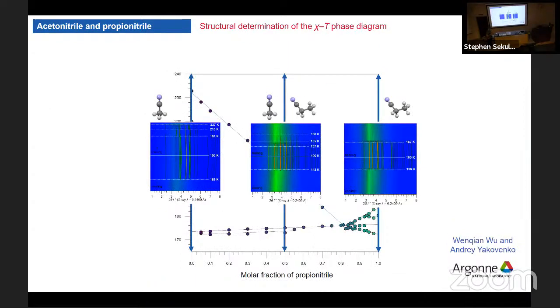As I said, we can get all of this information just by looking at the boundaries, but very similar to the case of propionitrile and acetonitrile, we really don't know what is going on here. And the only way we can learn is by doing diffraction and solving all of those crystal structures. And this is exactly what we did. So we first followed pure acetonitrile, then pure propionitrile, and then we went ahead to cover the rest of the phase diagram. And as I said, a lot of these phases are unknown, so let's talk about it.